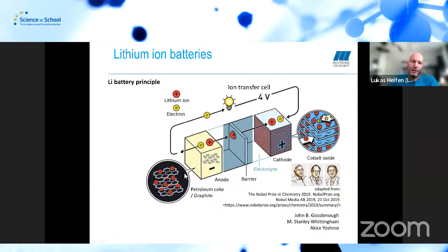That means during the charging, you store the lithium in graphite, in the interlayers here. And upon discharging, it releases an electron, and the ion goes through a separator, a barrier, via an electrolyte, and goes to the cathode. Sorry, that was a bit too fast. At the cathode the same principle applies again: the ion gets intercalated into NMC, for instance, or cobalt oxide cathode materials. For the intercalation, you generally create stresses and volume expansion, so over different charging and discharging cycles the material works, expanding and contracting.